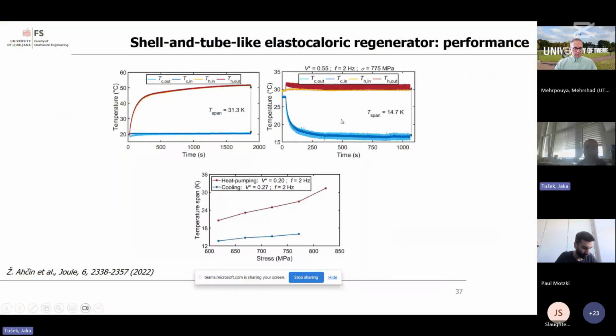As you can see, the temperature profile is starting to build, and it will reach steady state conditions after a certain amount of time. Let's say the cold side temperature is around 20 degrees, and the hot side temperature was about 45 degrees, which means in this case we reached 25 kelvins of temperature span in the heat pumping mode. We tested this device both in heat pumping and cooling mode, where we reached 31.3 kelvins in the heat pumping mode and half of that in the cooling mode.